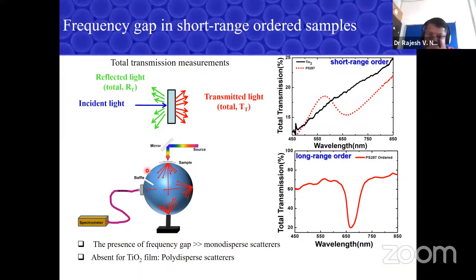So we have a small setup which is called an integrating sphere. You keep your sample here, you pass your white light laser, connected to a spectrometer, and you can measure. It's a very easy measurement. It's not very difficult or anything. So even a master student can easily do it. Okay. So we measure total transmission as a function of wavelength, and this black curve is for a sample of TiO2 powder, the paint, the TiO2 powder or the chalk powder kind of thing. And you can see that as your wavelength decreases, the transmission decreases, as expected for any disordered medium.